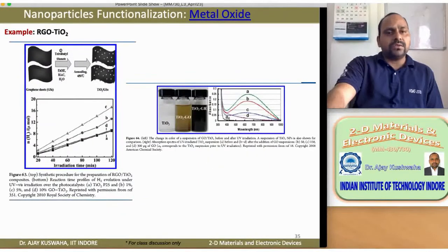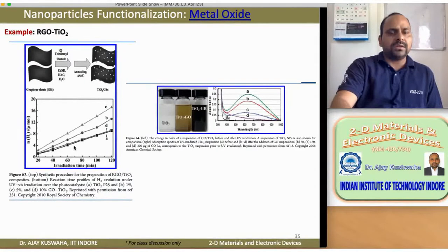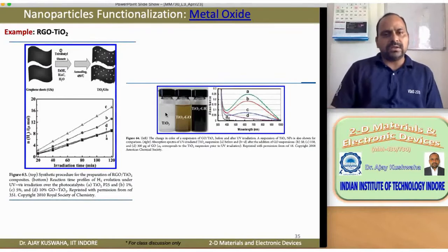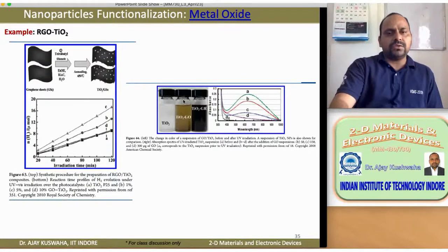Other is RGO-TiO2, which has shown the TiO2 modified graphene, and they have demonstrated that when we are exciting this material with UV light, the hydrogen production amount is higher when we have a mixed material. Third, even here they have shown the change in color. TiO2 is almost milky or whitish in color. When we have TiO2 GO, it's brownish in color. Once you reduce this, the suspension becomes TiO2 and reduced graphene oxide, so slightly blackish in color. And here you can see the clear-cut difference in the absorption peak.